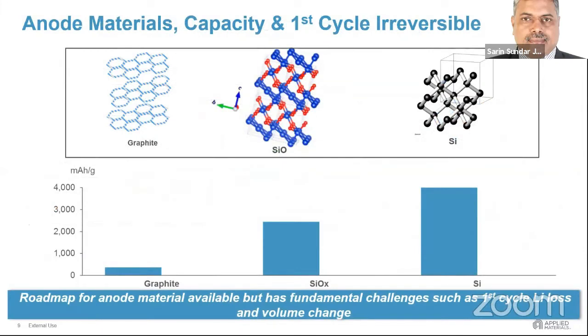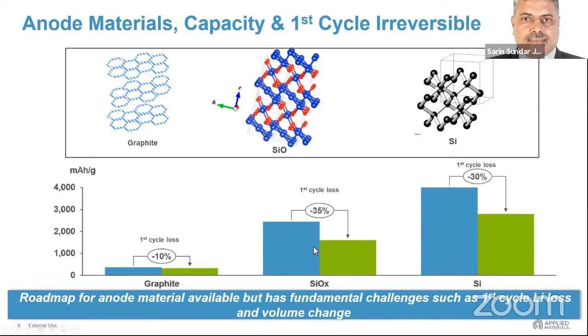One other thing we are targeting is the first cycle irreversible loss. If you look at anodes, whether graphite anodes or SiOx or silicon anodes, typically these were the energy densities. During the first cycle, the formation cycle, graphite batteries have about 10% energy density loss. This corresponds to a loss at the cell level, and at the pack level it will be much more.